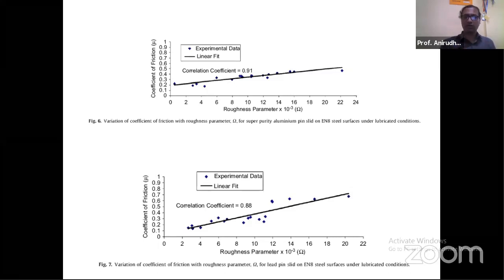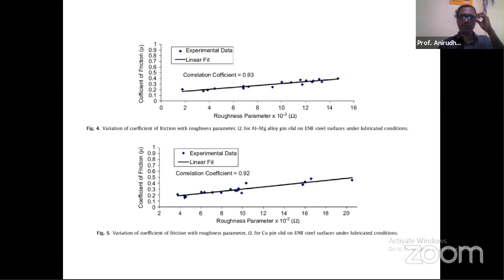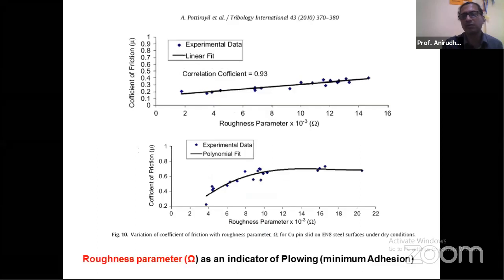Now, these correlation coefficients are quite high. They are of the values of 0.93, 0.92, etc., which means, taking nearly the square of these values, that a correlation coefficient of 0.9 means nearly 81% of variation in coefficient of friction can be largely explained in terms of RQ, which is descriptive of the peak values of distribution, and the other parameter which is indicative of the frequency of packing of different asperities. And so we find a very large amount of coefficient of friction explained.